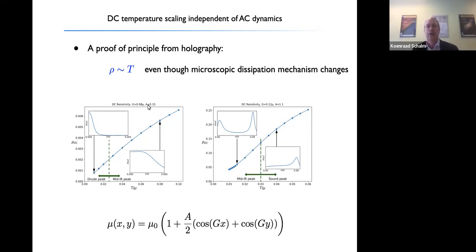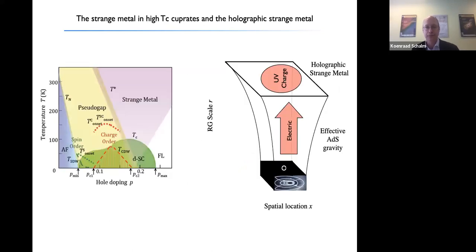This is the system where we computed this, and here you see the lattice wavelength and the amplitude in this system. So let me now explain in detail where this signature comes from and how it can be that you have this resistivity that is essentially insensitive to the microscopic dissipation mechanism, which you visibly see changing, but the temperature scaling of the resistivity does not.